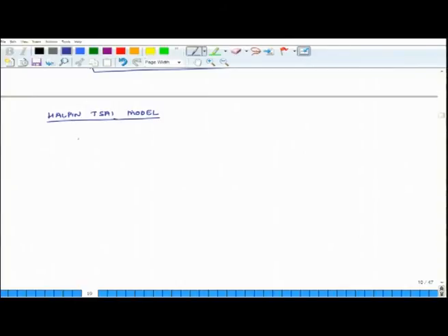So, what does the model say? It says that GLT divided by Gm equals 1 plus zeta eta Vf divided by 1 minus eta Vf.